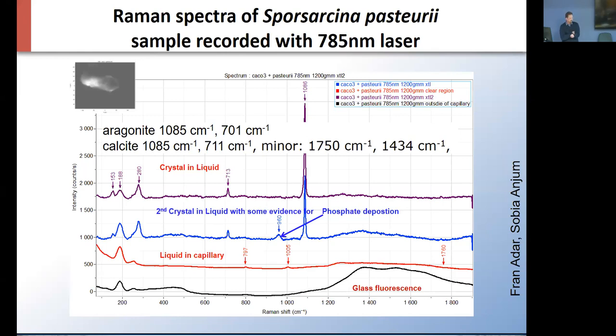For XRD and SEM and some of the other methods, we have to have much larger aggregate sizes in order to get that information. Now, again, this looks like it's easy. Well, it's not. Depending on how your crystal, your aggregate, is oriented, you might or might not get a good Raman signal. So it is better to have a flat surface in order to do this, but it can be done even with naturally grown crystals, aggregates inside a flow system.